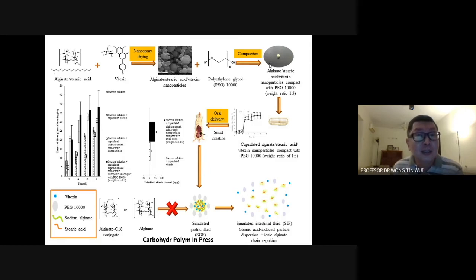So the trick in this entire exercise is that stearic acid remains the most important excipient in order to maintain the dispersibility of the nanoparticles in the intestine from the compact, as well as drug release. Now let's take a look at the mechanistic diagram. In the gastric regions, due to the PEG and the alginate, the drug release is rather minimal, but upon prolonged transit into the intestinal regions, the polyethylene glycol will dissolve and release the nanoparticles.